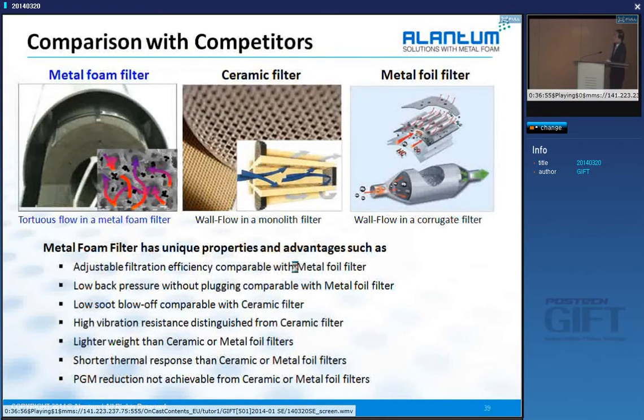Now I can compare the competitors in the filtering market. Definitely cordierite ceramic, and another one is the metal foil filter. So the benefit of using our metal foam filter is written here. Definitely we have low back pressure. Low back pressure avoids heavy plugging or stopping. We have very low soot blow-off, and we have high vibration resistance. Once you travel with trucks, off-road, all ceramic will be broken. But our metal foam never breaks, okay? So that's a good thing. And also very light, and I will mention some other examples later, but it has a much shorter thermal response. And the PGM reduction is definitely very low.